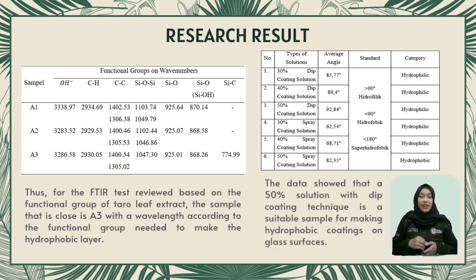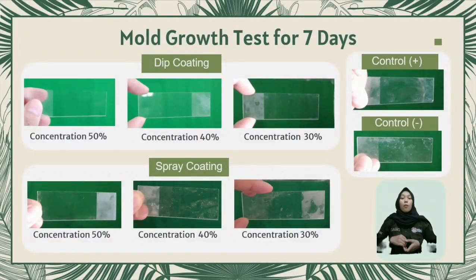The FTIR test reviewed based on the taro leaf extract. The best sample is the third sample with a wavelength according to the functional group needed for make hydrophobic coating. And then for contact angle test, the best sample is the dip coating technique with concentration 50% and average angle at 92.84 degree and can be said hydrophobic, cause have contact angle more than 90 degree. Then, for mold growth test for 7 days, the dip coating technique with concentration 50% is the best.